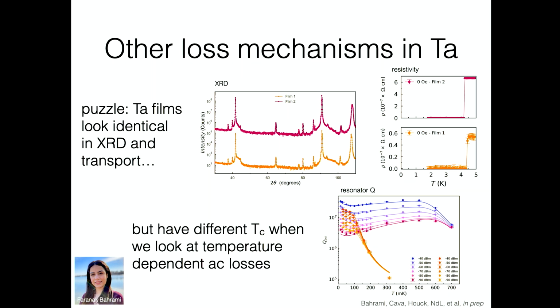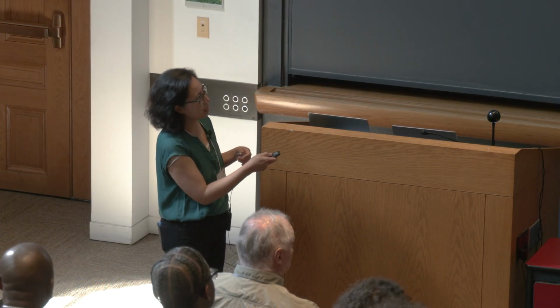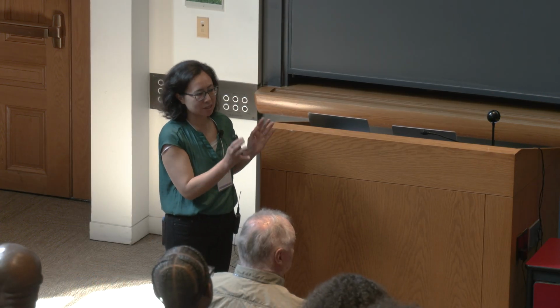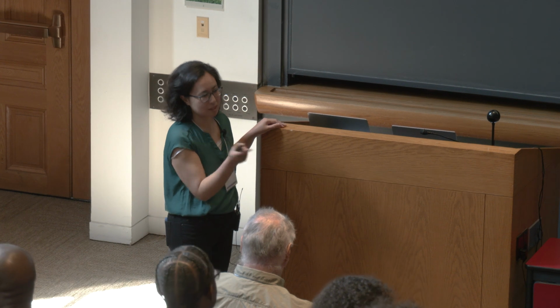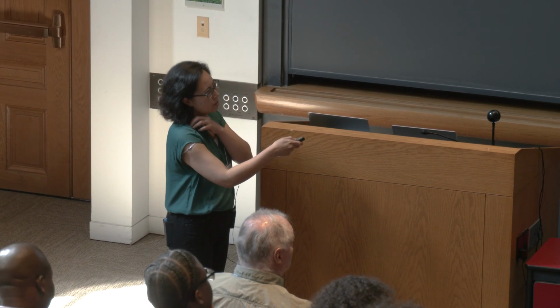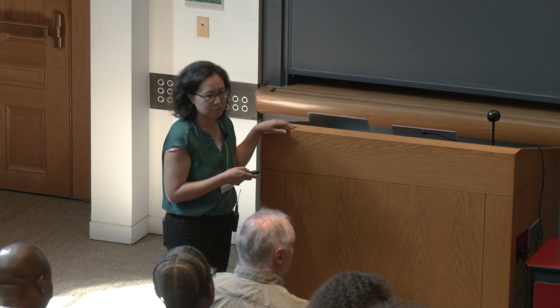So when we do this power and temperature dependence, in general, when these things start to kind of come together and drop exponentially, one of the ways that you get that is with quasi-particles. So you just break Cooper pairs and you make quasi-particles, and then those give you resistive loss. So in some sense, it's a measurement of the critical temperature of the superconductor. And that's how we were interpreting it, which is why these are all labeled as high TC, low TC, or whatever. It turns out you can get the same behavior with vortices dragging around. But the key thing is, where do you start to see the onset of this exponential loss?